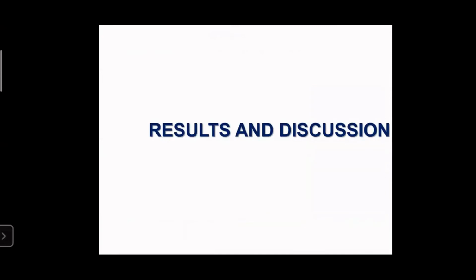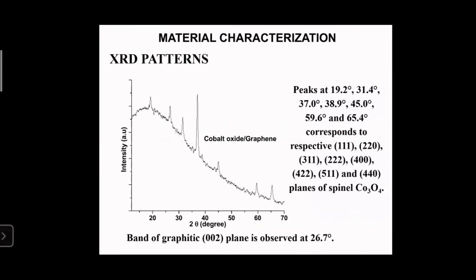About the results and discussion. First, we analyze the X-ray diffraction patterns of the nanocomposite. From the XRD patterns, it is clear that we are getting spinel Co3O4 as the cobalt oxide phase. And usually, it is not so widely reported for highly crystalline Co3O4 graphene nanocomposites. In most cases, the Co3O4 spinel is found to be more or less amorphous in nature, but here, comparatively, we got well-defined peaks for the Co3O4 spinel.